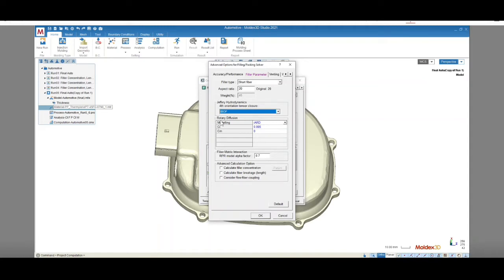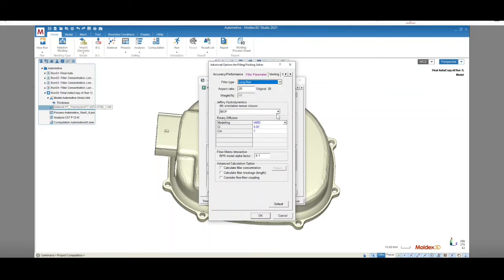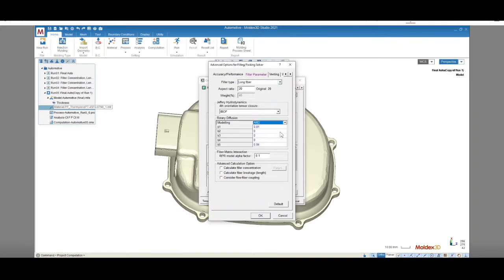The second approach is Rotary Diffusion. It includes three options, the Folgar-Tucker, the ARD, and the IARD model. The options for Long Fiber Analysis include IARD and ARD. ARD accounts for the fiber-fiber interactions with anisotropic rotary diffusion, which help to better capture the Long Fiber Orientation Distribution profile. The drawback is that there are five parameters to set.